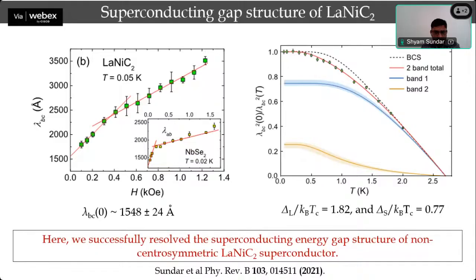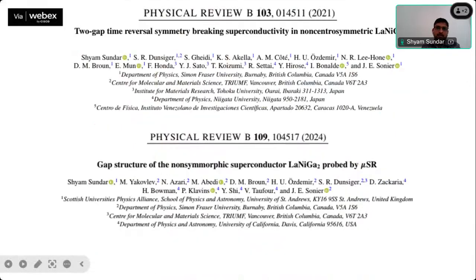And now this is one of the researches. This is lanthanum nickel carbon 2. A similar compound called lanthanum nickel gallium 2 also was proposed to show the same kind of behavior, and it was proposed that the superconductivity in these two materials is pretty much of the same type. So we also resolved the superconducting gap structure in the lanthanum nickel gallium 2 compound, which is basically compositionally similar to lanthanum nickel carbon 2.